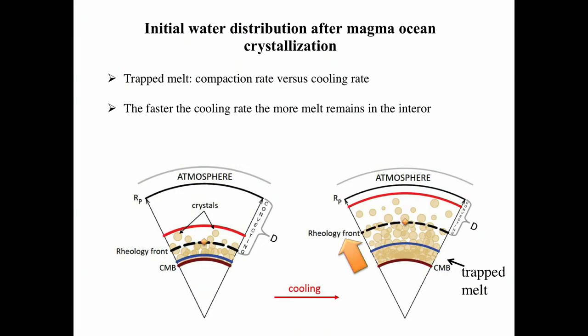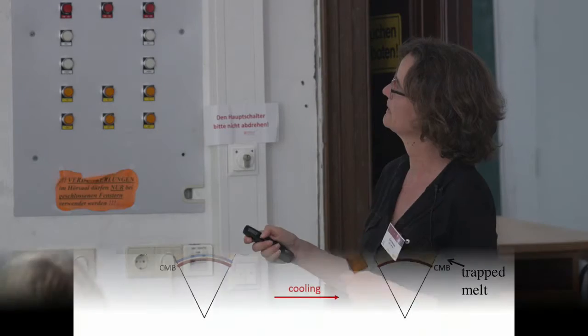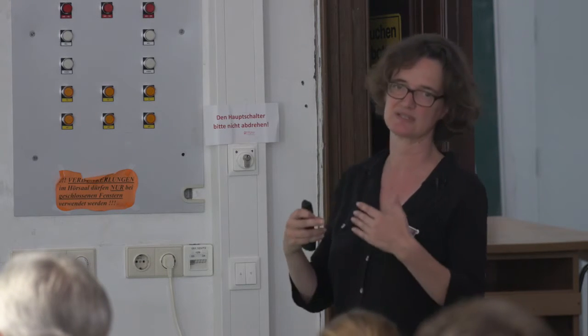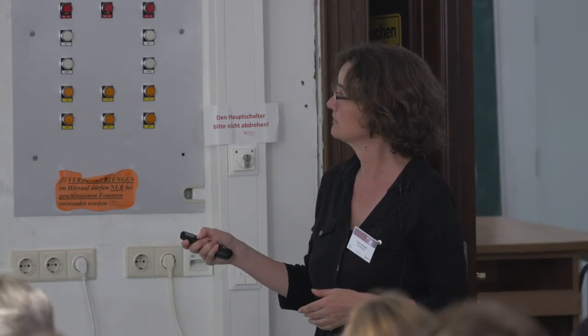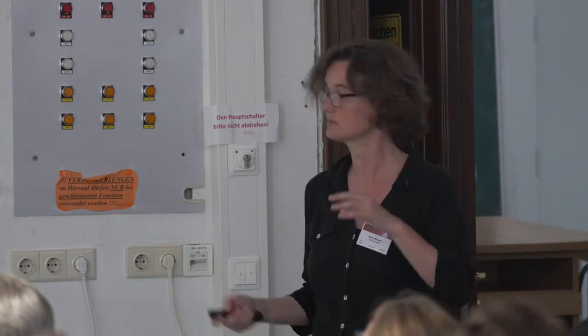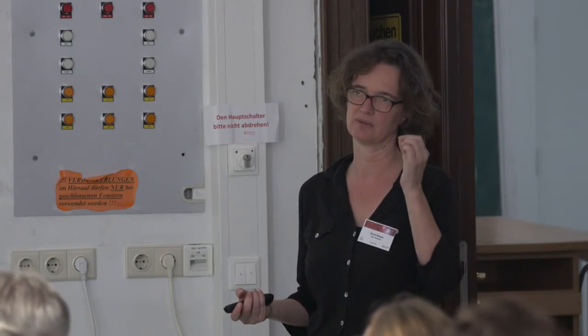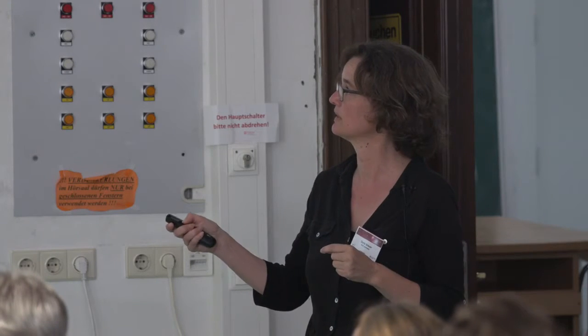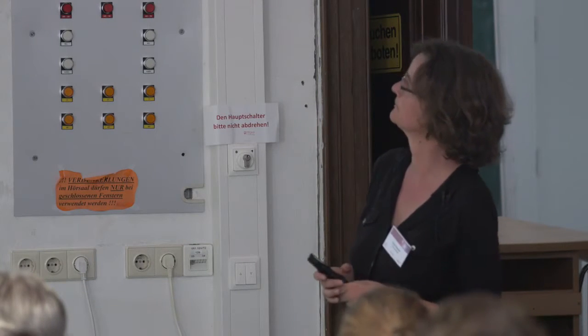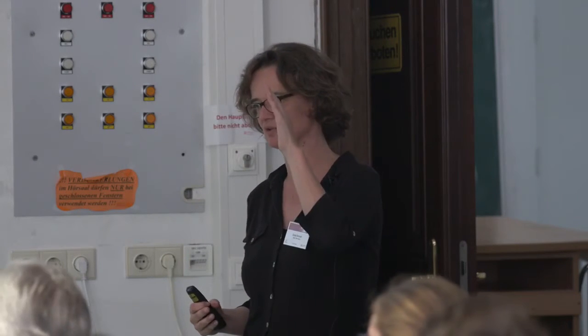But if the cooling were slow, that melt could rise up and you would have no or less melt in that region here. So in other words, the faster the cooling rate, the more melt remains in the interior. And what we see from magma ocean crystallization models is that the cooling rate is extremely fast. So the models even argue that you can trap a lot of melt here, which means, if you remember, water is in the melt. So you can trap not just melt, but also volatiles in the interior of the planet. Is that somehow clear? So that's a mechanism again. Degassing by crystallization is very efficient, but this is a way to keep some water in the interior.